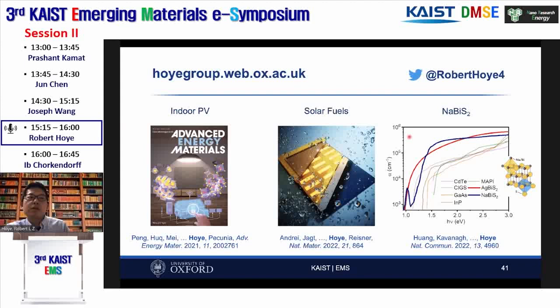And also, we've measured the exciton binding energy through optical measurements, and we compared that with our calculations. The exciton binding energy is very low, below 20 meV. So that would suggest to us that even though we have a small size of 4 nanometers, we avoid the formation of excitons in the system. But perhaps if you were to reduce the size further, maybe then you would have an exciton-dominated system.